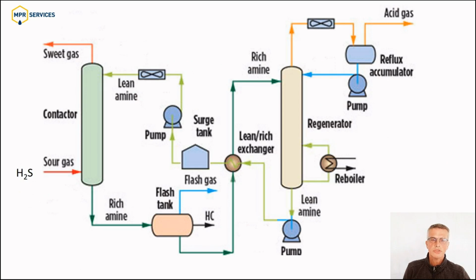Let's concentrate on corrosion and on chelation here. The amine system needs to be protected from corrosion. The species which cause the corrosion are the acid gases that the amine system is actually designed for, H2S and CO2. We cannot eliminate them. Therefore, we need to make sure that what protects the amine system from corrosion stays in good shape. That is usually the passivation layer, but can also be a protective layer like cladding, or sometimes the metal itself,